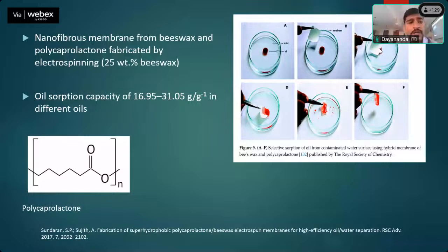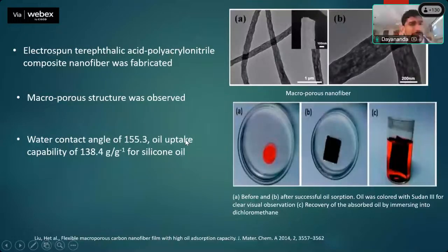This mat was fabricated by taking beeswax and polycaprolactone, with oil sorption capacity of 16.95 to 31.05 grams per gram for different oils. This fabricated nanofiber mat was a little different but more efficient than the previous work, where the contact angle was measured and it had the ability to absorb silicone oil.